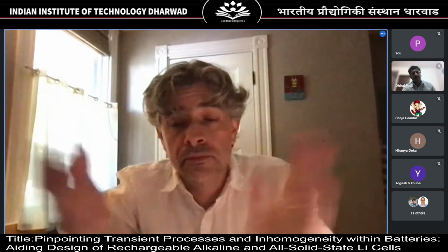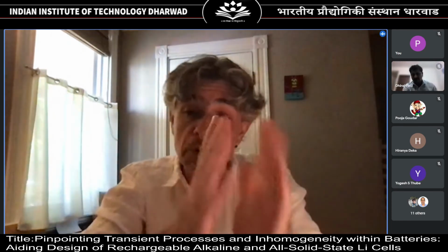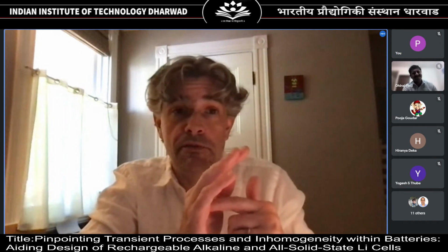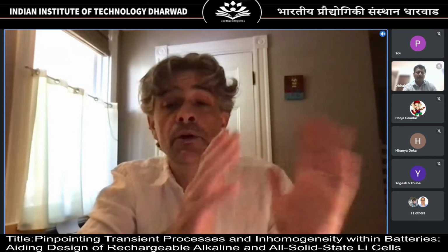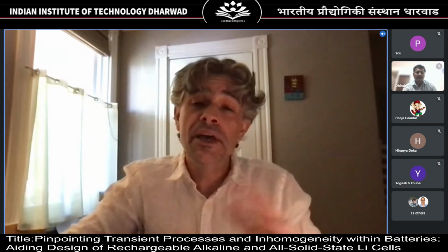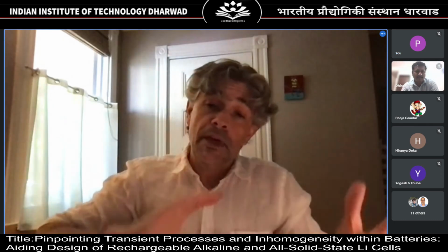So, it was speculated some 20 years ago that you could make a solid electrolyte that would be so strong that it would stop lithium dendrites from forming in the battery. And it turns out that lithium dendrites are... I don't know the current research on it, but can you make something that's so strong that it can stop a lithium dendrite from growing to the cathode? It's an open question.